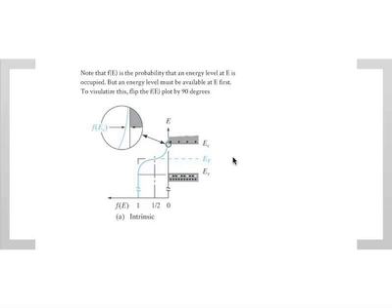Now, if we have an intrinsic semiconductor shown here, we know that there are no energy levels in the band gap, no donor levels, no acceptor levels, which means that no electrons can exist in the band gap with that energy because there are no available levels. Although the probability of that energy being occupied here is non-zero, there are no energy levels available, so there are no electrons. So you have to multiply these two things together in order to understand how many electrons there are.